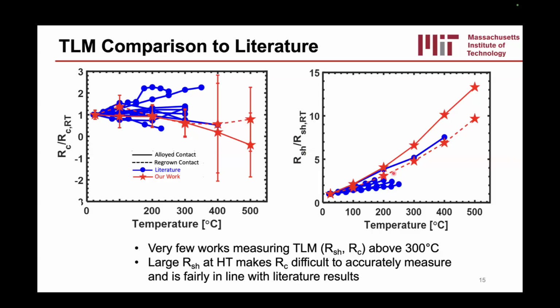Similarly, if you look at the sheet resistance, once again, you can see there's a lot of data points at 300 C and below. And this trend is the same as ours, but there's not a whole lot beyond that. And so we're trying to understand what's going on at these higher temperatures. And you can once again see here, the sheet resistance significantly increases as a function of temperature. And up to 500 C, it's about 10 to 15 times higher than it is at room temperature. And so we want to understand what is causing this really high sheet resistance.